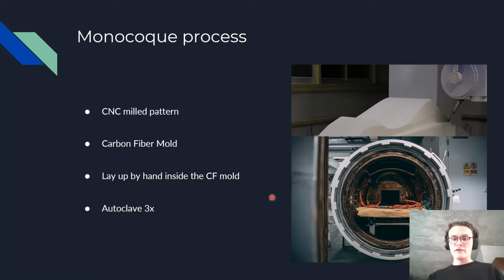To do that, another layer of epoxy is added, and then the honeycomb is added on top of the epoxy. It has to get cured again now to attach the aluminum honeycomb to the carbon fiber. So into the autoclave it goes again, gets cured once more, and comes back out. And then finally, the outside/inside layer of the monocoque can be added, and again it goes into the autoclave and comes out, and that's your part done.